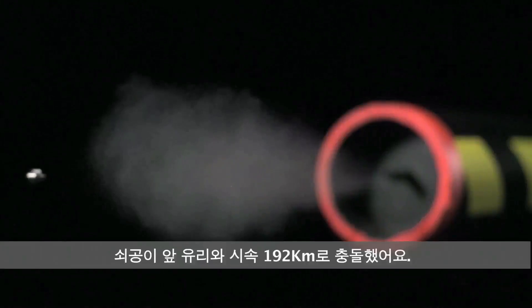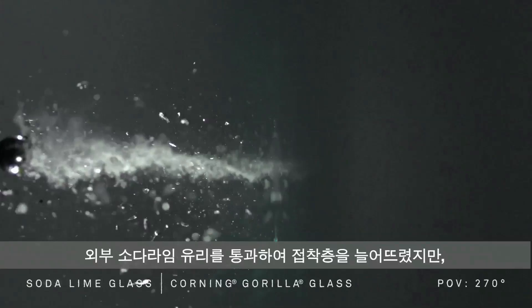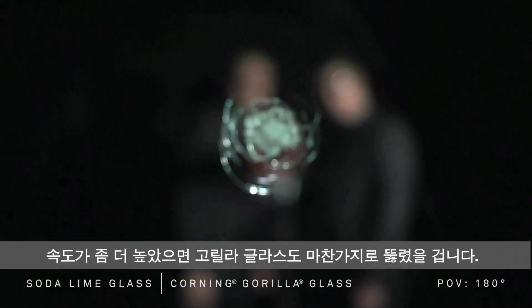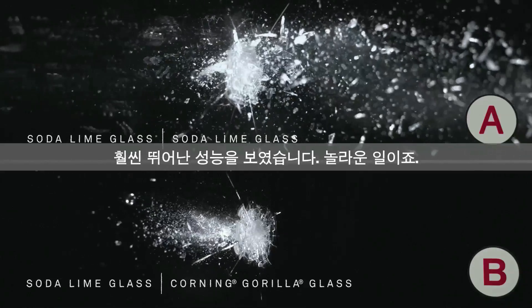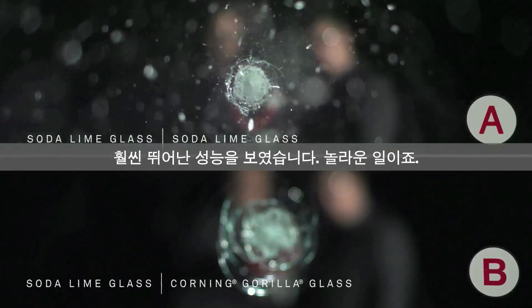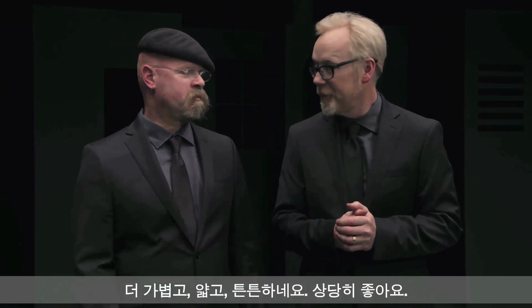So let's try windshield B. The Gorilla Glass didn't appear to break — the foil is intact. The ball bearing hits the windshield at around 120 miles per hour, just as before. It goes through the front layer of soda lime glass, stretches the resin, but doesn't have enough energy to break the Gorilla Glass. It's not bulletproof — I'm pretty sure if we turned up the velocity we'd breach the Gorilla layer too. But in this test, and all things being equal, it performed a lot better than the thicker, heavier soda lime laminate windshield. That's impressive. What we're seeing here is compressive strength at its finest moment.